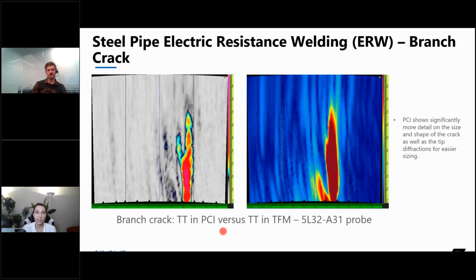And then lastly here, another ERW indication, which is a branch crack in this case. And we can see it very well on the conventional TFM with the blue background, very loud signal. But we know that this is a bit more true to geometry here with the branch crack, and sizing will also be easier to do with the PCI, having hot tips to place the cursors on. So this is another advantage here.